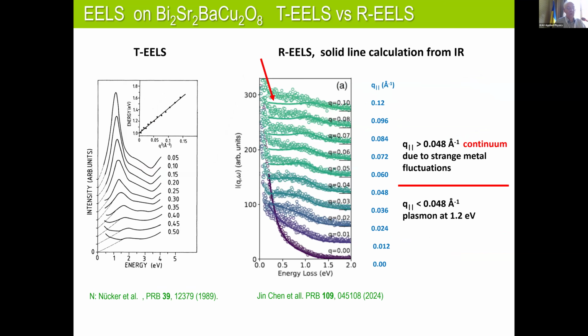Now, on the left side, I show you our early data on the plasmon dispersion in Bi2212, a bilayer system. And you see a quadratic dispersion, and we see a well-pronounced plasmon below the critical wave vector, where the plasmon moves into the continuum. This is roughly at about 0.5 inverse angstrom. And this is contrasted with reflection EELS from the Urbana group, and at lower momentums they interpret these data by a plasmon excitation below 1/10 of the critical wave vector, and then at higher momentum they believe they see a continuum. So they support, at least at higher momentums, this idea that the plasmon should be overdamped.